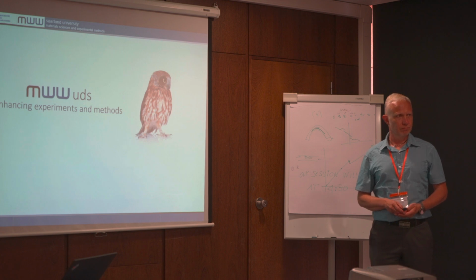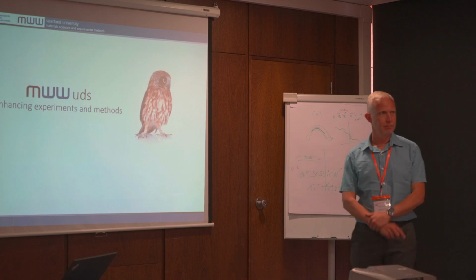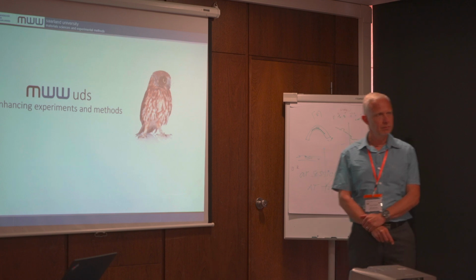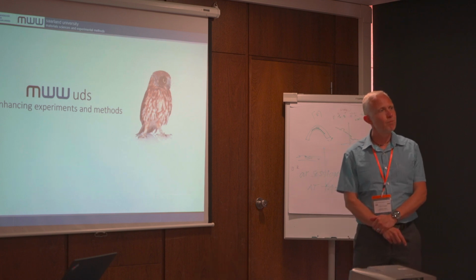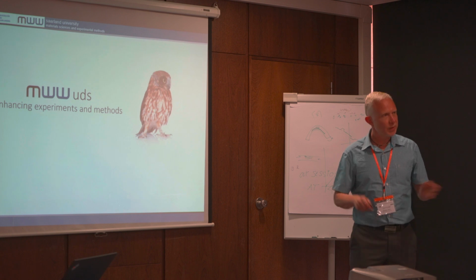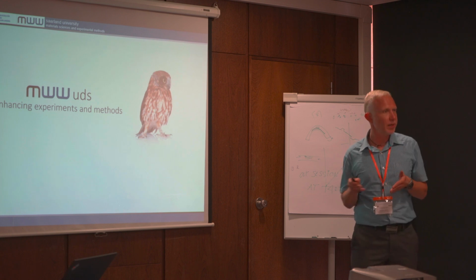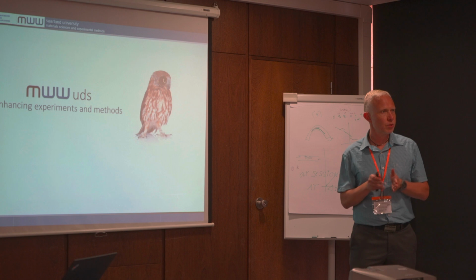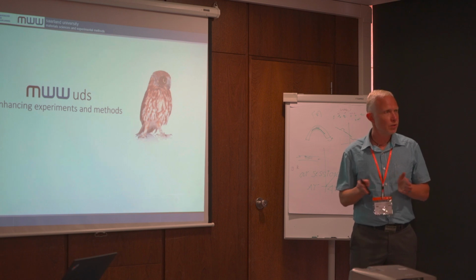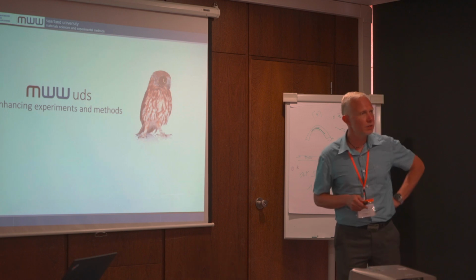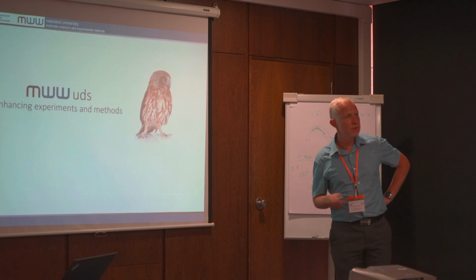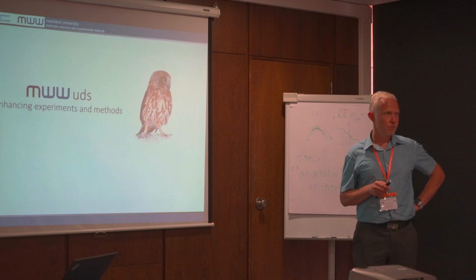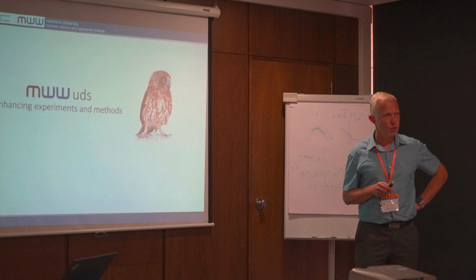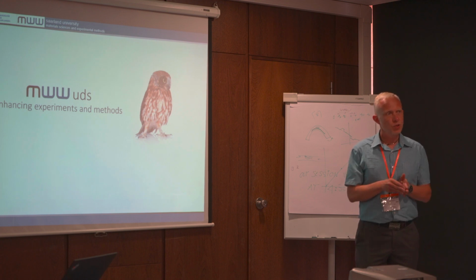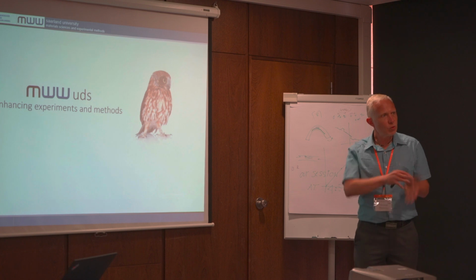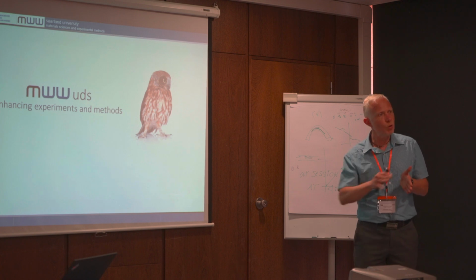Yes, please. Hi, I'm probably being an idiot, but I thought you could only measure elastic strains with X-ray diffraction. So how do you measure plasticity? Sorry. Yeah. So what we can measure here is the strain, actually, because we measure it by the strain of the crystal lattice in the XRD. But this is what you get from your different kinds of measurements. Sometimes you measure strain, sometimes you measure stress, and then you calculate it at the boundary where you have your yield strength.